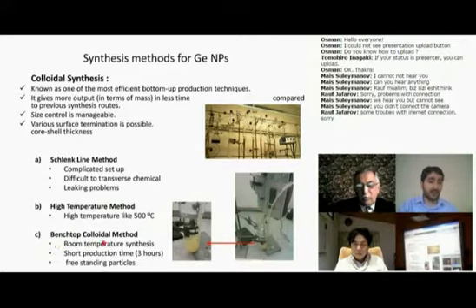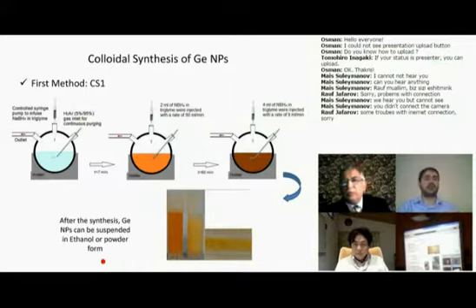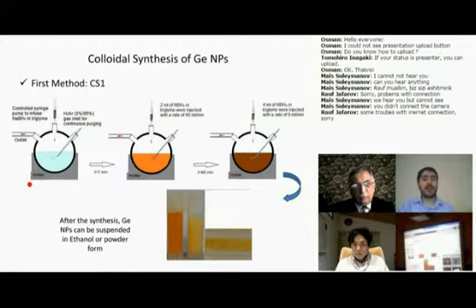What we are using here is the benchtop colloidal method. It's very easy, and you can do it with room temperature synthesis in a very short time. In 3 hours, you will be able to produce your particles, and they are freestanding, so you can have core nanoparticles. Okay, let's talk about the details of our particles.